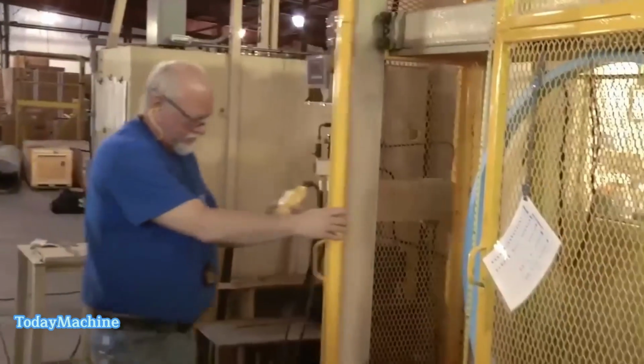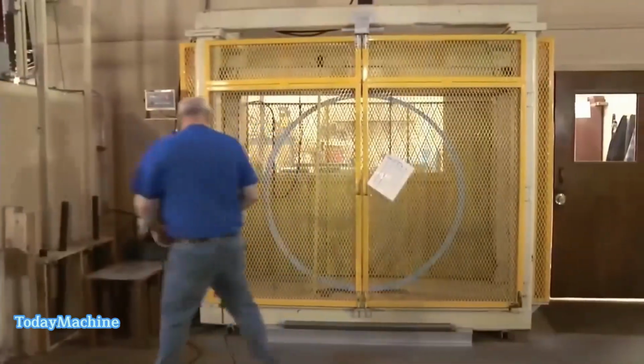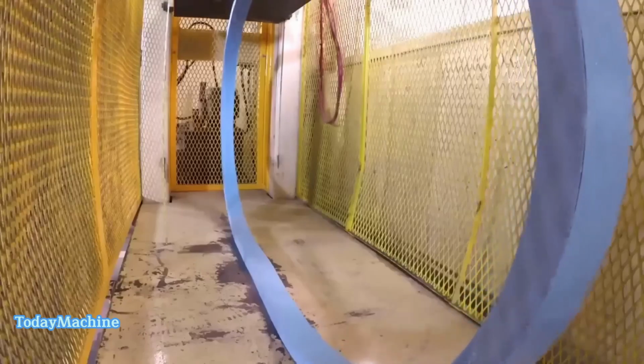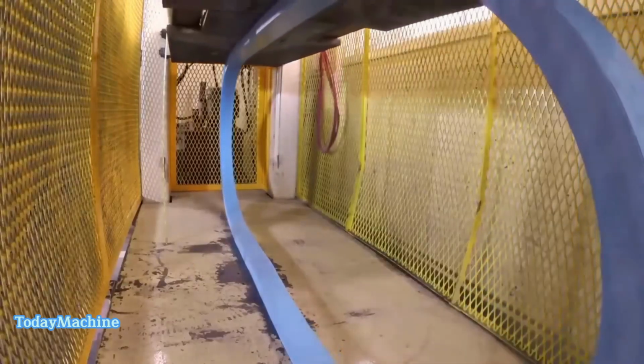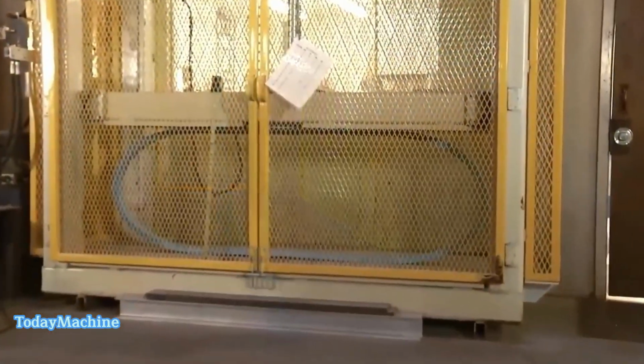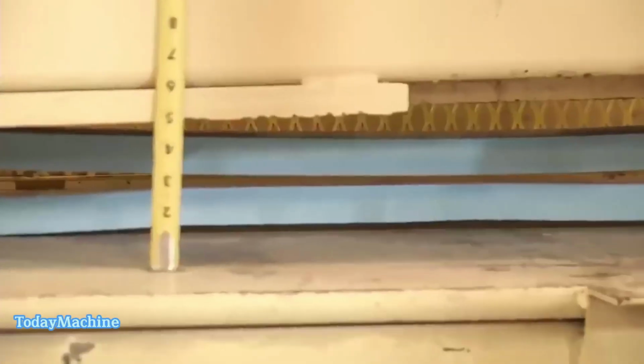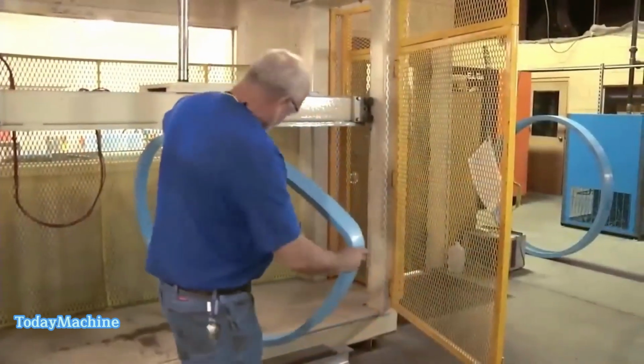This test assesses the ability of the pipe's wall to withstand impact by subjecting it to the force of a 20 or 30-pound weight. The weight is raised to a specific height and then dropped onto the pipe wall. Any cracks or breaking observed in the pipe would indicate a failure, highlighting the importance of its impact resistance.